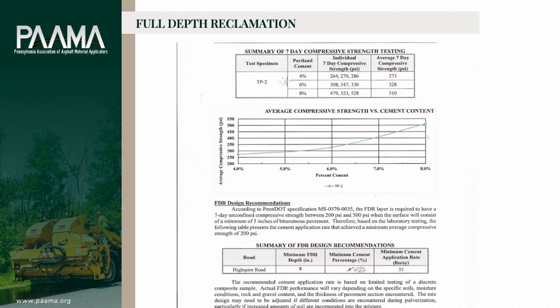Well, we really can't. One way we can stop that is after about a week, go back with a dual spool vibratory roller and vibrate the whole mat. You will put hairline fractures in that Portland cement base, which will then expand and contract with the weather, and it won't crack the road. If you don't do that, you will have block cracks. They will come about. It's simple fact. It gets too hard. So we have to be careful when we're doing a mix design in a lab to what we produce out in the field.